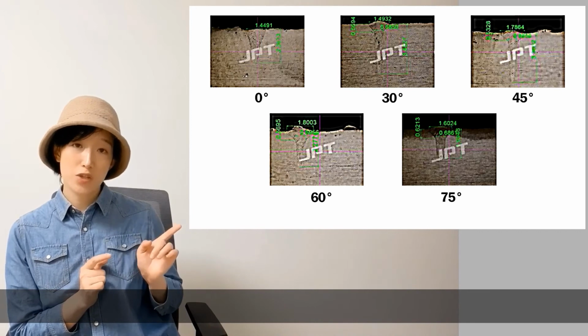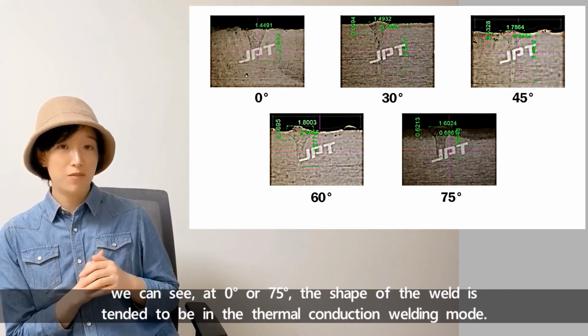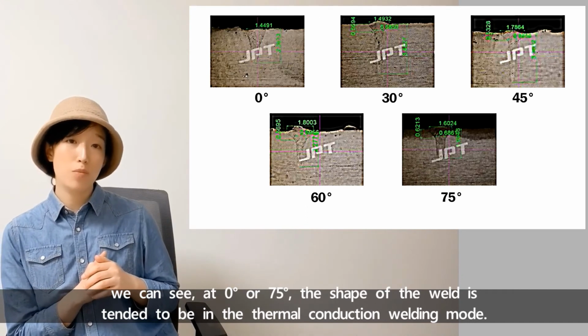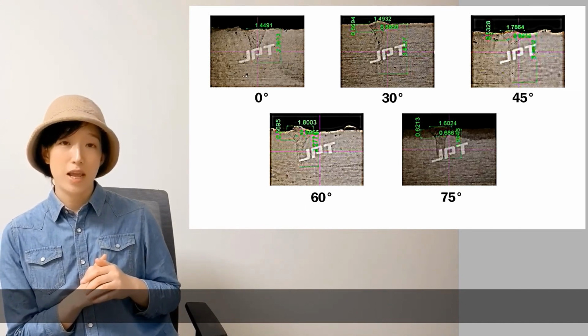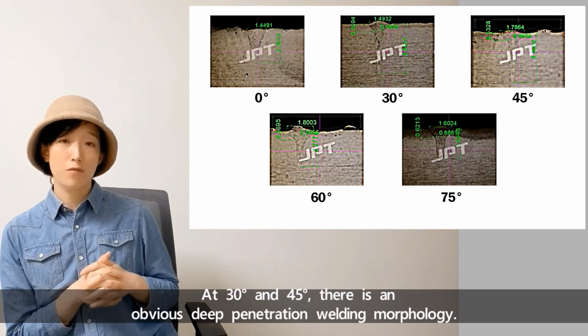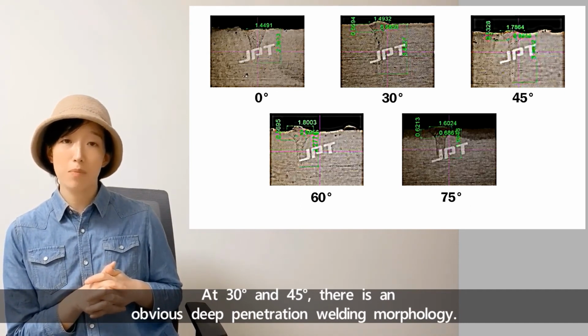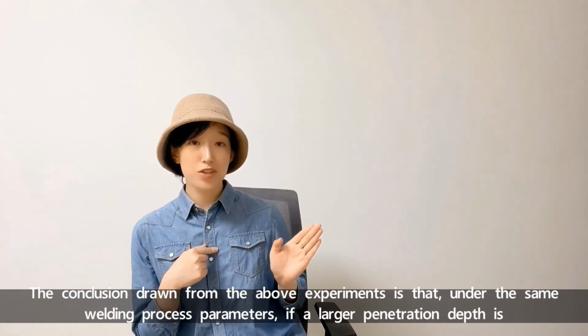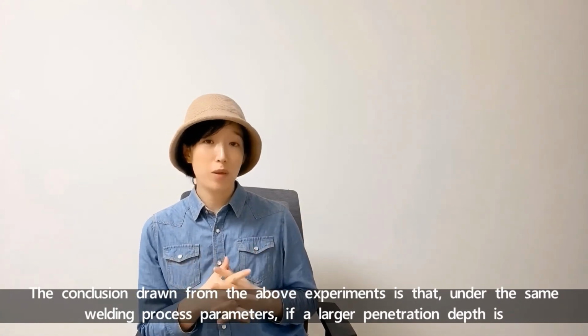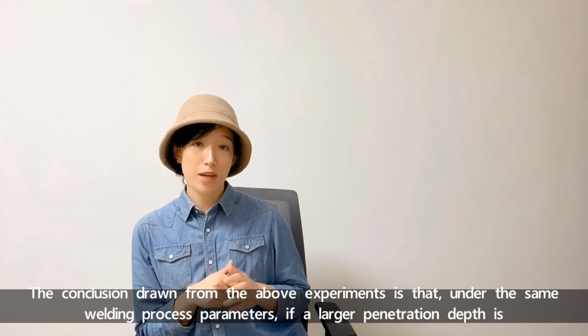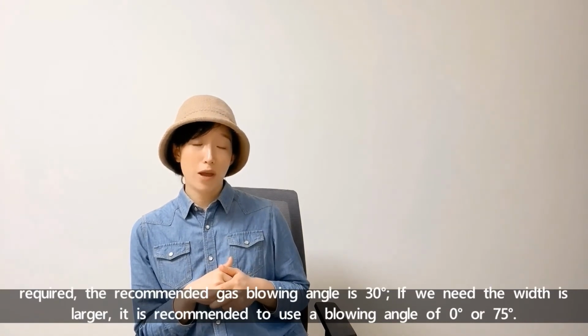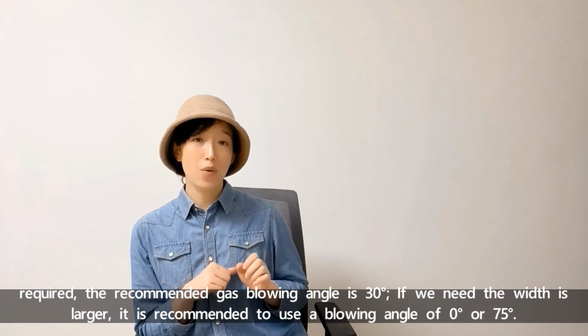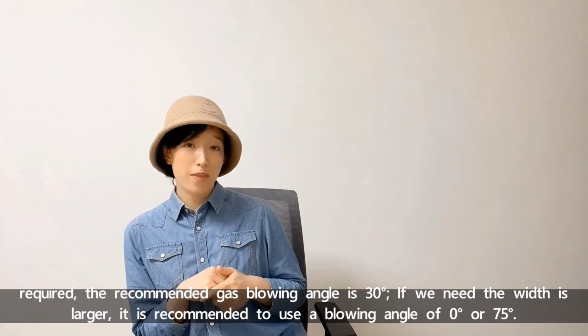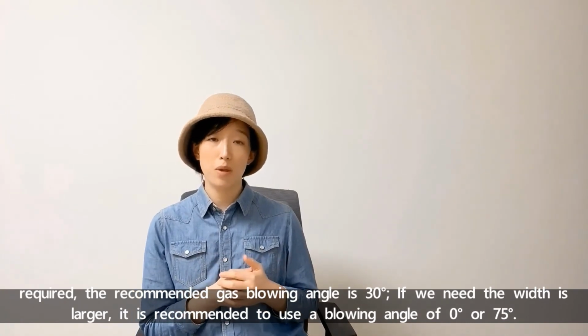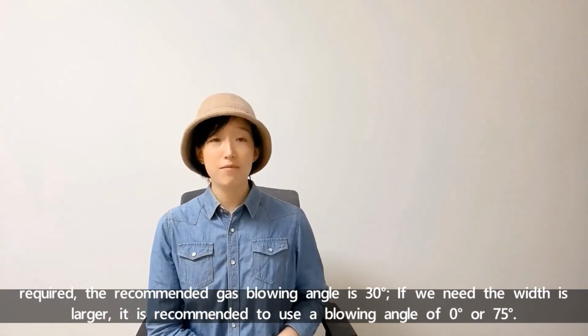From the cross sections, we can see that at 0 or 75, the shape of the weld tends to be in the thermal conduction welding mode. At 30 and 45, there is obvious deep penetration welding. The conclusion drawn from the above experiments is that under the same welding process parameters, if a larger penetration depth is required, the recommended gas blowing angle is 30. If we need a larger width, it's recommended to use a blowing angle of 0 or 75.